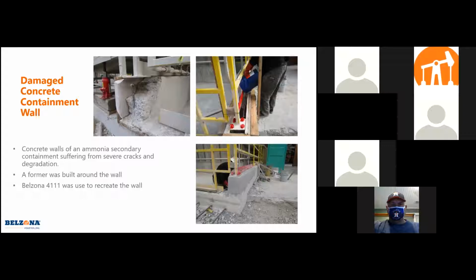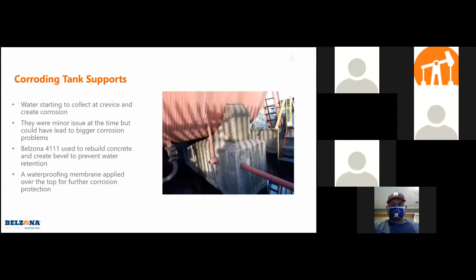The good thing about this material is you can create whatever consistency you want. So you can add less aggregate or more aggregate to make it a different consistency, to make it easier to pour. So you can see they poured it in, let it cure. Normally full cure in 24 hours. This is a scenario, kind of a proactive approach. They had a tank sitting on some concrete supports here, and they were having some crevice corrosion right at the tank support. So it's a minor issue at the time, but if you let this gather up over the years, you can have some through wall defects and some bad corrosion.